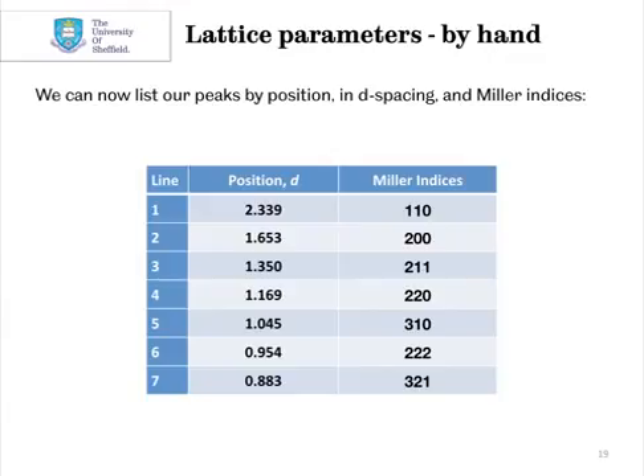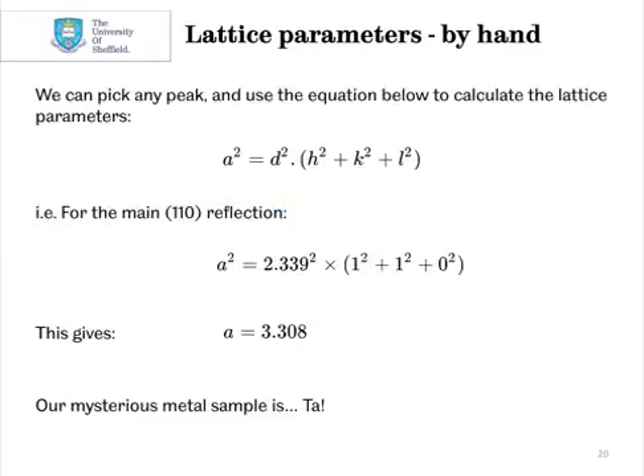Next, we can compare this. So we've got our d spacings and our Miller indices for the peaks, and this is all the information that we need to calculate the lattice parameters. We can pick out any peak and use the equation that we derived a second ago to work out the lattice parameters. So for example, for a 110 reflection, we found this at a d spacing of 2.339 angstroms, so we can plug those values into the equation, and that gives us lattice parameter a of 3.308 angstroms. If you remember the possible values we were given earlier, we can now confirm that our mysterious metal sample is in fact tantalum.